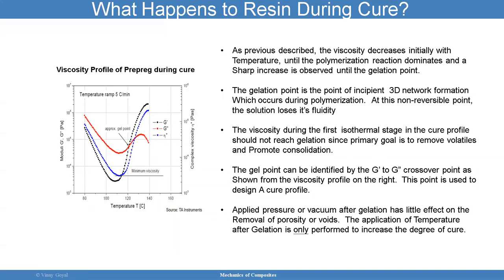The viscosity during the first isothermal stage in the cure profile should not reach gelation, since the primary goal is to remove volatiles. So first I want to be able to promote consolidation. That's the first thing I want to do, and I really need to make sure I'm achieving that by getting to a low viscosity state. And I get to low viscosity by increasing temperature.